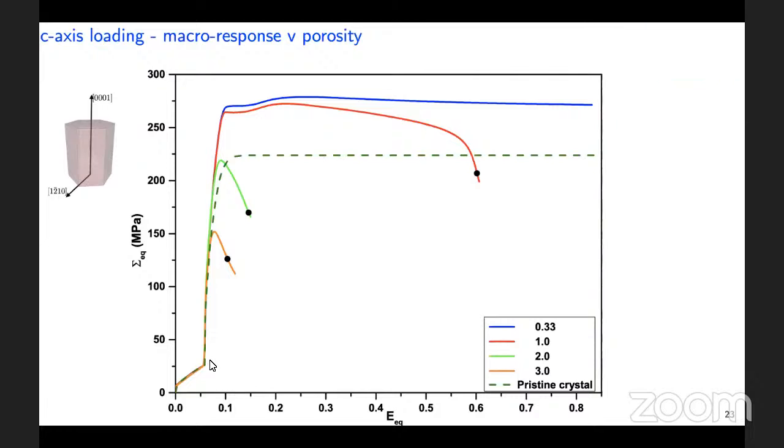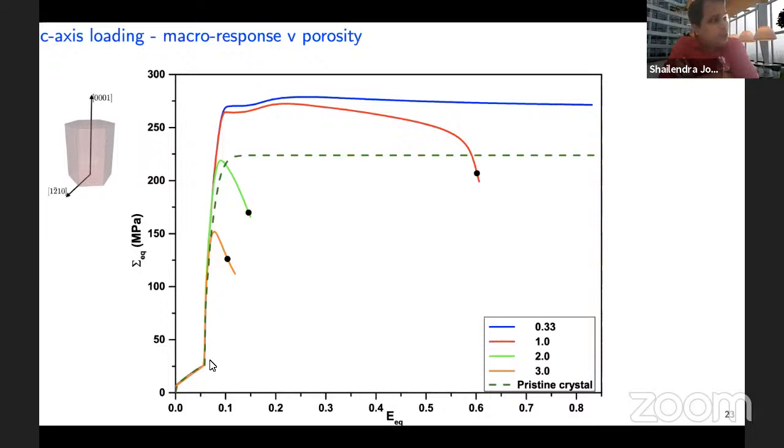Right. The reason I asked that question is that the 2D simulations which we had done, the analog of this using cylindrical voids, actually show shear localization, essentially caused by pyramidal C plus A. But the 3D ones are not clearly indicating that. But as you said, it could be twin-induced coalescence that could possibly take place in that situation. You're right. We did not observe any shear localization in this case.